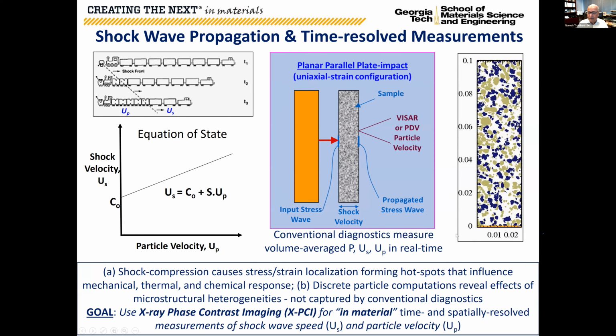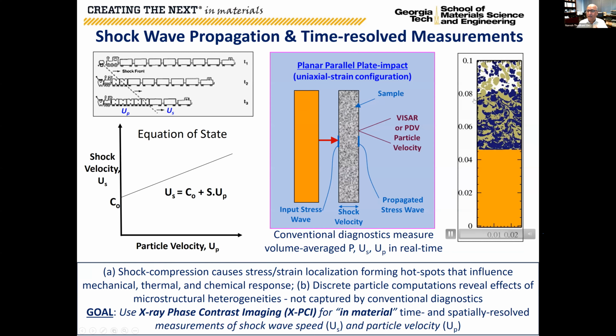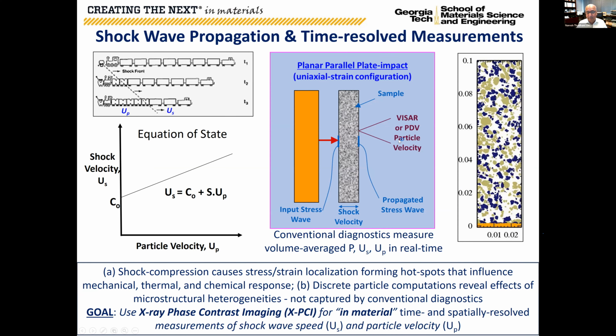Let me show you a result of a simulation of an experiment where the shock was generated upon impact, and you can see that front moving ahead of it. You can see the turbulence as well as the heterogeneous nature of the wave front as it is moving. The diagnostics that we typically use are unable to capture those effects, although simulations clearly reveal that there are a lot of things happening inside the material, leading to, for example, stress strain localization, which can create hotspots that influence the types of changes we are interested in monitoring. These are really very clearly revealed by computations, but never really captured by conventional diagnostics.